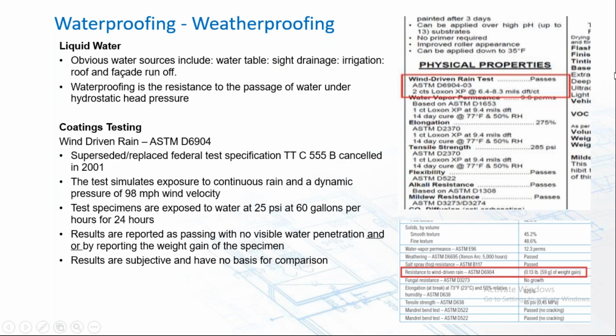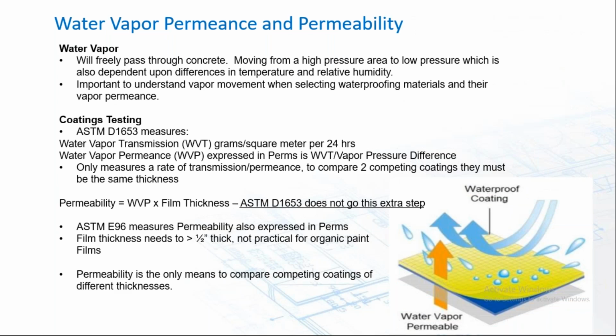Water vapor permeance and permeability. And this is a real mind bender. There are 4 different tests: wet and dry cup, as well as the ASTM 1653 and E96. But essentially, the coatings industry has really fallen in behind the ASTM 1653. However, what it does in the first process of its measurement is determine water vapor transmission, WVT, which is grams per square meter per 24-hour cycle.